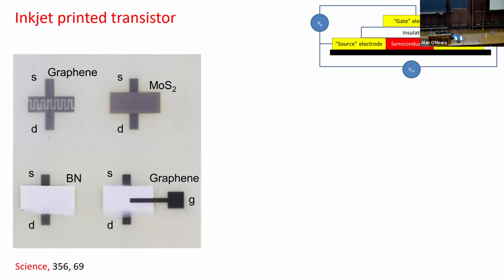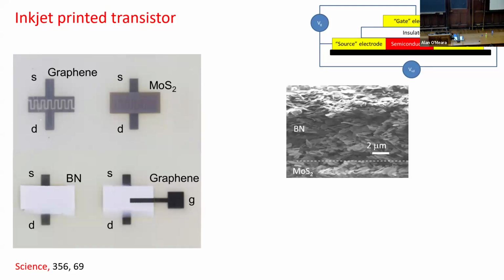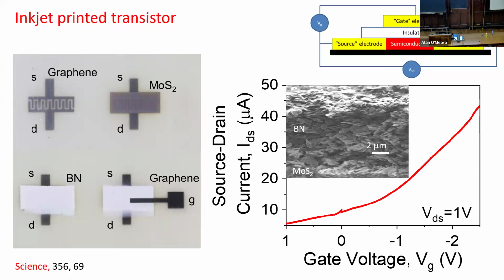And the idea is you apply a voltage between source and drain, no current flows until you apply a voltage to the gate and then current starts flowing. This is an electron microscope image of the stack. That's the MoS2 on the bottom and the boron nitride on top of it. And this is the current flowing as a function of the gate voltage. Now, it's not the best transistor ever made. In fact, I'd venture as far as to say it's probably the worst transistor ever made, but it is the first transistor ever to be printed from all 2D materials. And now this is a whole field in itself. It's moved on a long way since then.